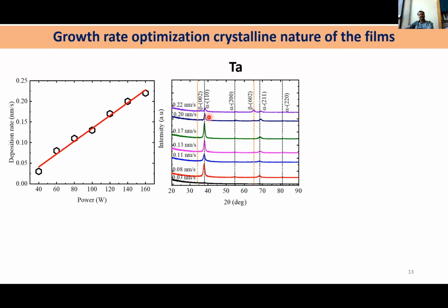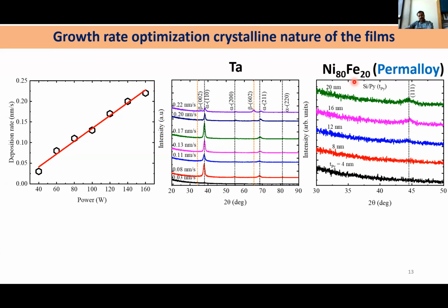And in terms of nickel iron permalloy, which we have chosen because of its low damping parameter, we deposited permalloy at a particular deposition rate, that is 0.1 nanometer per second. When we change the thickness, we found that we are seeing the crystalline phase only from 12 nanometer thickness. Up to 4 and 8 nanometers didn't show any crystalline phase.